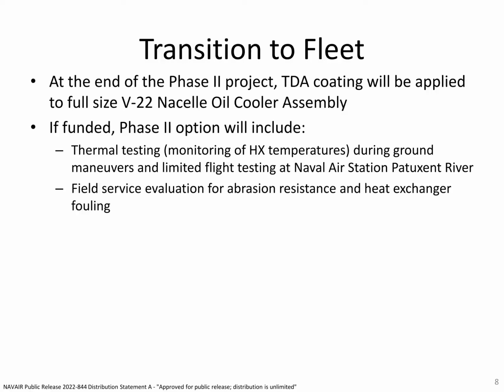The test aircraft is then taken through ground maneuvers and limited flight testing, during which the heat exchanger temperature is monitored. This testing should demonstrate that our coating does not affect the heat transfer efficiency. Once this is complete, the coated heat exchangers will undergo a field service evaluation to determine the abrasion resistance and the expected reduction in heat exchanger fouling. This testing will give us a body of data that will drive the transition to the fleet.